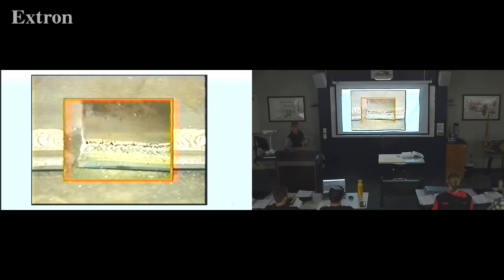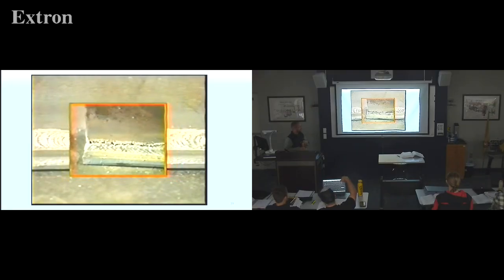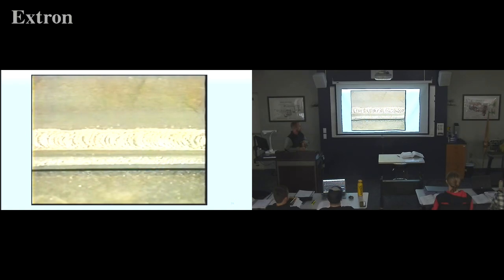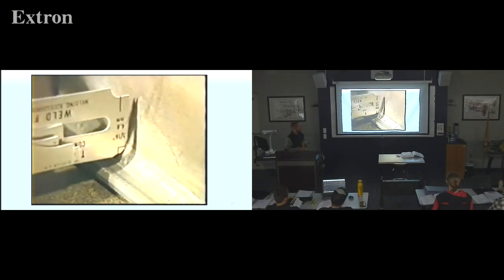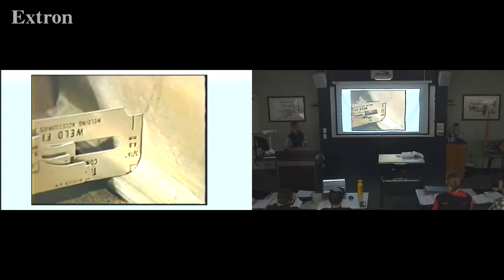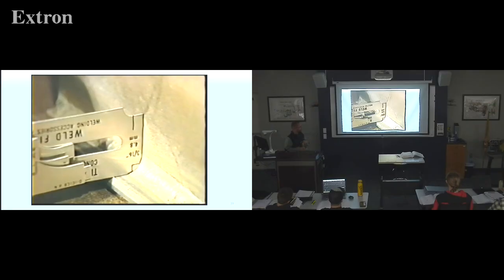The weld shall be acceptable if undercut does not exceed 1/32 inch in width, 1/32 inch in depth, and has no more than the combined total of 2 inches of undercut in any 6 inches of weld. Bead profile. The fillet weld should be flat to slightly concave with equal legs approximately 3/16 inch long. The face should have a smooth, even contour.